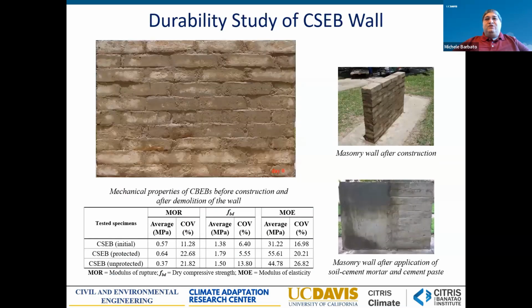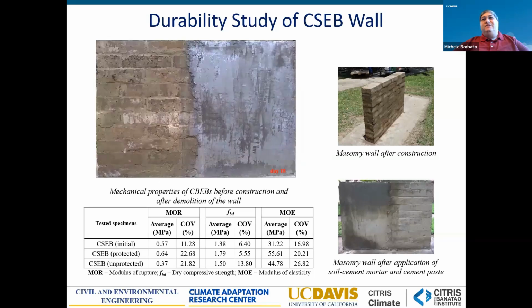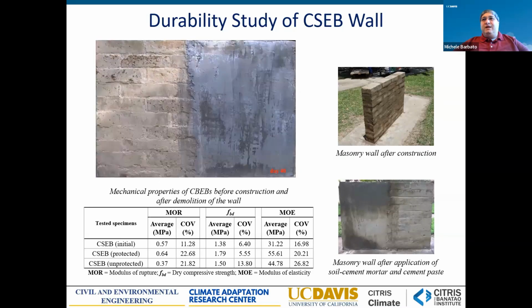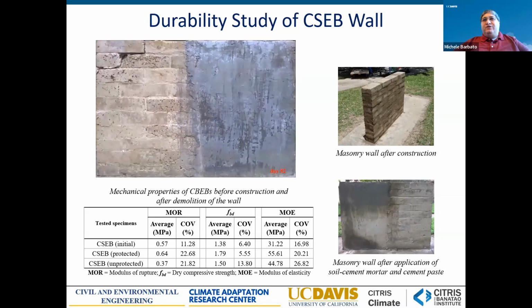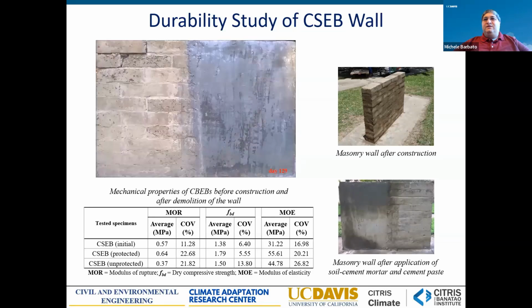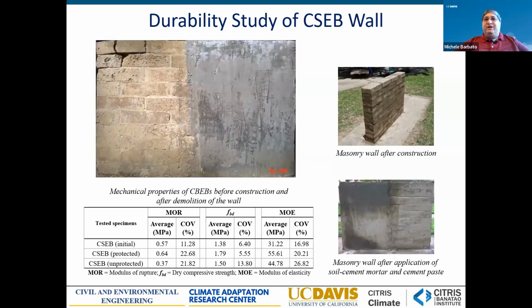The first issue that we wanted to identify is how do we protect this material from the wet, humid conditions of southern Louisiana. Here you can see the results of a test that we did by building a small wall outside of the LSU campus where one side of the wall was protected with a composition of soil and cement similar to the one used for building the blocks, and the other was left unprotected.